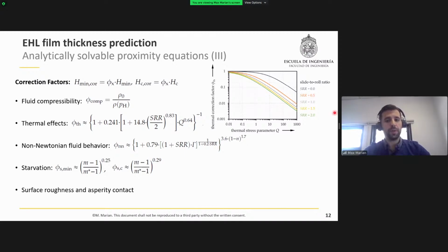Similar to thermal effects, non-Newtonian fluid behavior or shear thinning of the lubricant occurs at high speeds and at high slip. This can also affect the minimum film thickness and also change the profile in the contact center. Therefore, a number of authors came up with different correction factors. This, for example, an equation suggested by Bair, which also contains basically the slide to roll ratio, the Carreau exponent n, and the Weissenberg number. So basically, there are also some correction factors available.